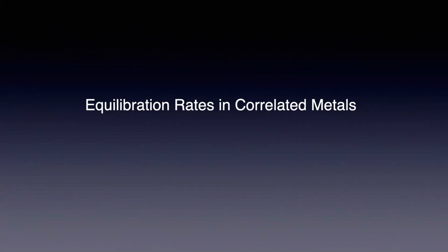One of the things that comes out in a very model-independent way is what resonances we see. We change the temperature, we use a narrowband pulse, and the amplitude mode comes into resonance with the driving field. And how it comes into resonance, and how many times it comes into resonance, matters. The amplitude mode is when the driving frequency hits 2 delta, but you can use 1 photon to get to 2 delta, 2 photons to get to 2 delta, 3 photons to get to 2 delta.